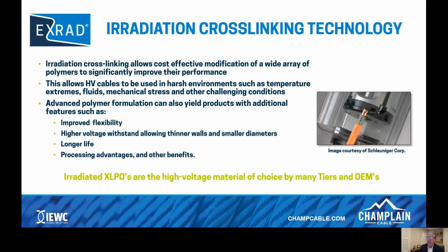So irradiation cross-linking allows cost-effective modification of a wide array of polymers to significantly improve their performance. So we're not just working with polyethylenes. We can work with EVAs and linear low density polyethylenes and high density polyethylenes. There's a number of materials that we think of as a palette, like an artist's palette of materials that we can choose from to create our material and optimize its performance. And this allows our high voltage cables to be used in harsh environments such as temperature extremes, fluid exposure, mechanical stress, and other challenging conditions.